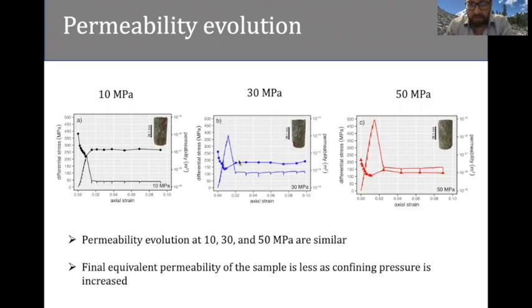And in both cases here at 30 MPa and at 50 MPa, we see that the permeability doesn't really change as the deformation is accommodated by frictional sliding. And so the evolution of permeability is, in the three experiments, qualitatively very similar. Quantitatively, what we can see is that the final permeability of the sample is less as the effective pressure is increased. So at 10 MPa, the final permeability of the sample was approximately 10 to the minus 17, and at 50 MPa, the final permeability of the sample was approximately 10 to the minus 18.